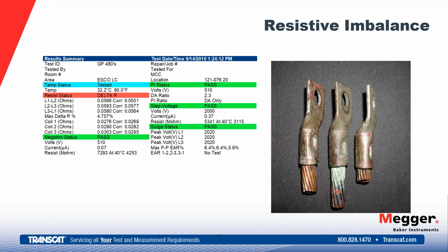Here's an example of a resistive imbalance at a paper mill. We've got a 4.7 imbalance. They went to investigate in this particular outage and they found connections that had corrosion on them, giving a higher resistance at that point, causing a voltage imbalance and current imbalance in that motor, causing high heat. So they replaced the connections and now they put that motor back onto a better curve.